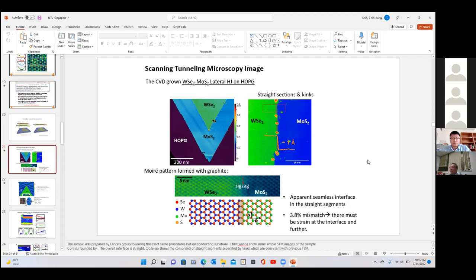What they have found is that doing STM on twisted bilayer is hard, because when you anneal it in UHV, the layers slip. So usually you put another layer of hBN to seal it. But with trilayer graphene, very interestingly, you turn it by theta, then turn the third layer back by minus theta, so the top and bottom are now at zero. After you anneal it, the top and bottom align extremely well. That makes moiré pattern fabrication for trilayers much more beautiful.